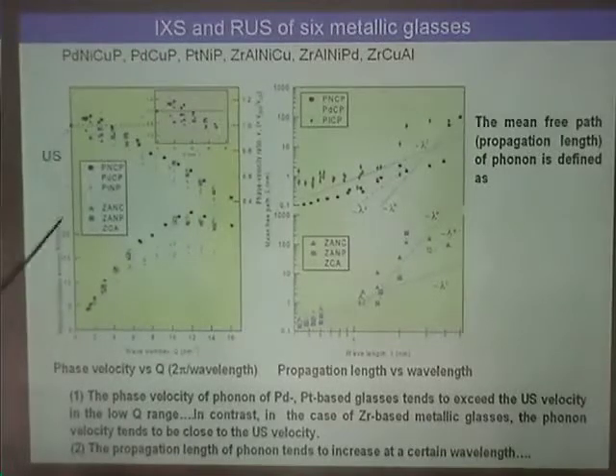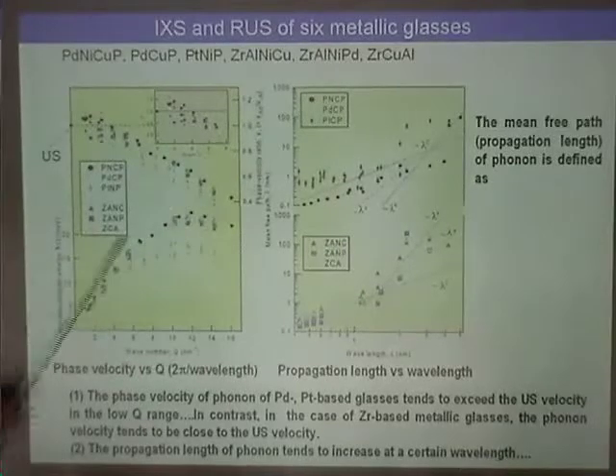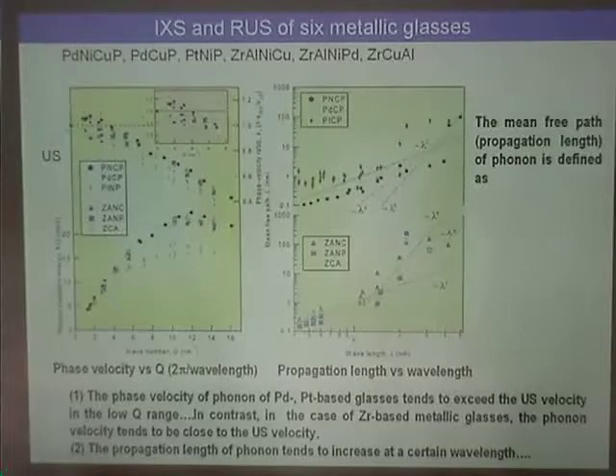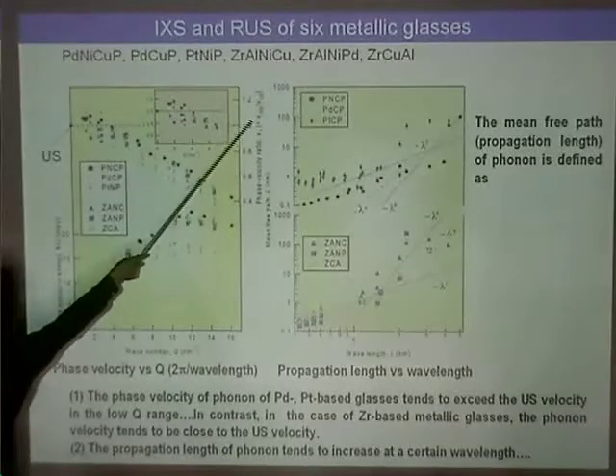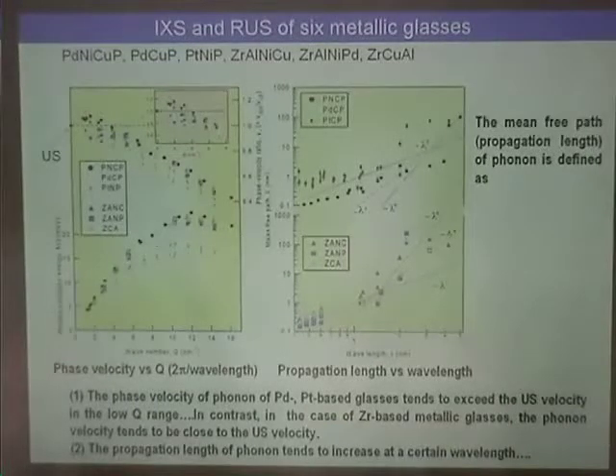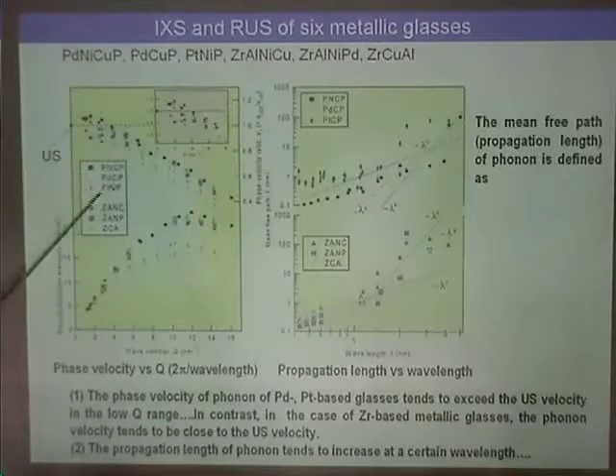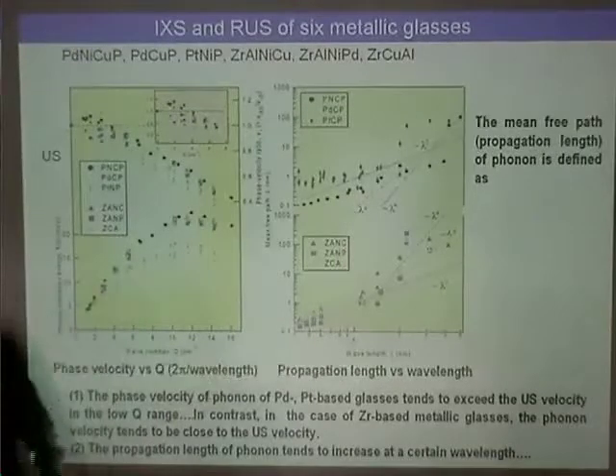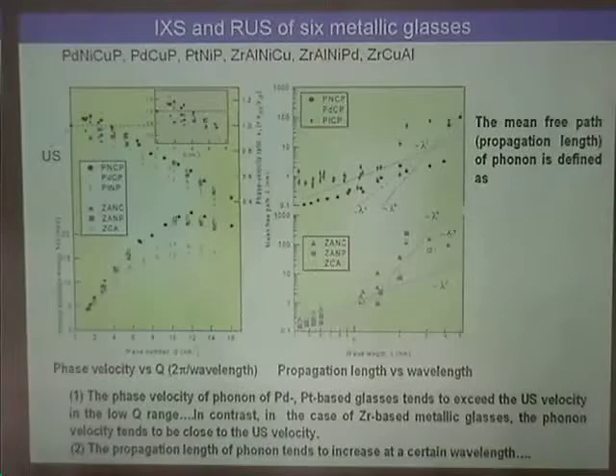And this is the phase velocity normalized by the ultrasonic sound velocity. This one means the ultrasound sound velocity. For palladium, platinum, and palladium copper phosphorus, namely these 3 metallic glasses, the sound velocities of the phonon exceed the ultrasonic sound velocity. And this is propagation length versus wavelength, where wavelength means lambda, the inverse of Q.